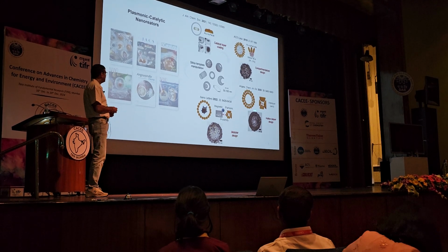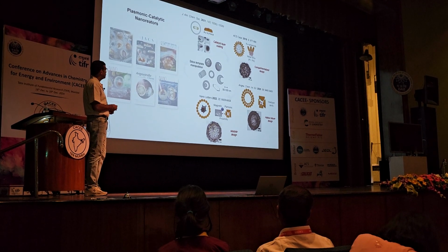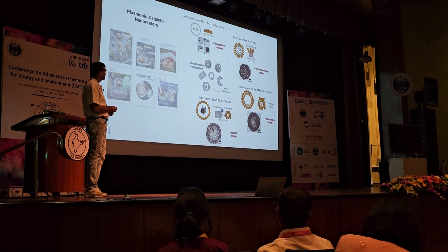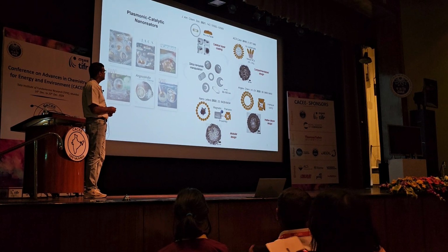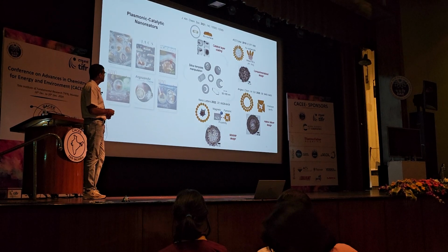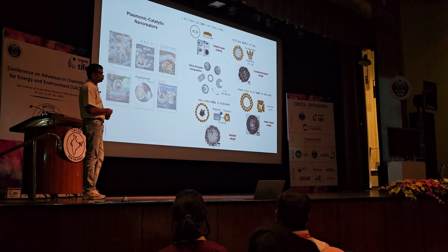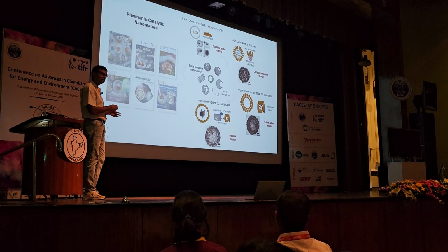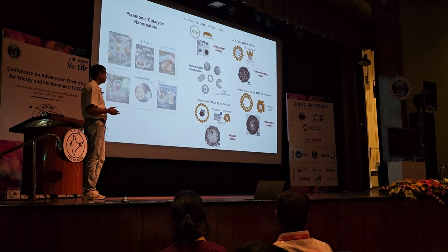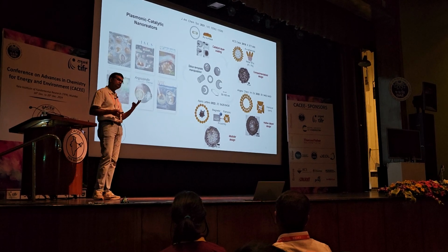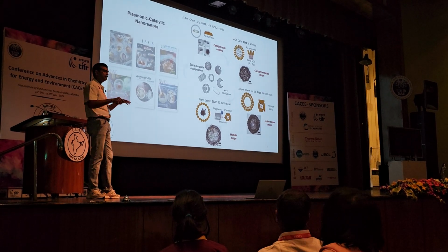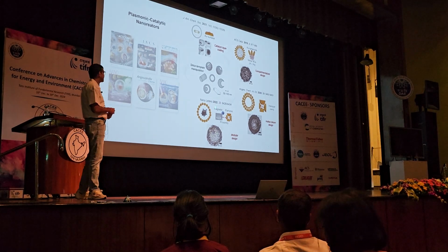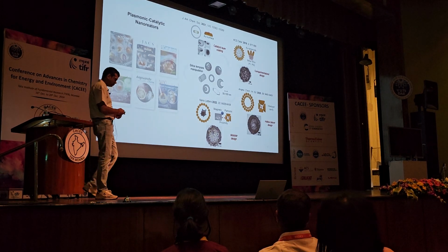Another design is a bi-layer design, where we can co-locate plasmonic hotspots with catalytic sites. These catalysts are very active for the reactions, and we can even couple two modules, like magnetic and plasmonic, together within a single nanostructure and perform two kinds of reactions, or two steps of the reaction, simultaneously, with each individually controlled by magnetic field and by light.